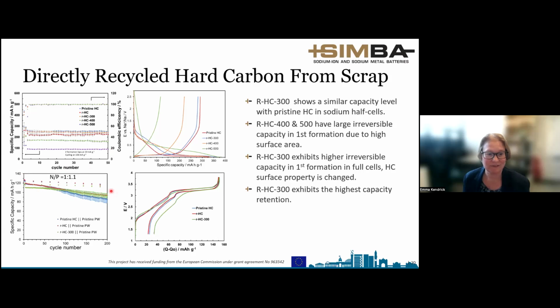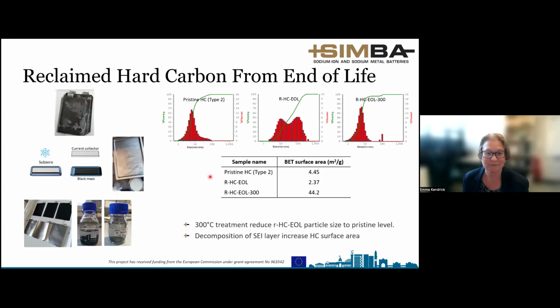Sticking this into a full cell, from the directly recovered, we can actually disperse this back into an ink again and recoat it, and it performs almost exactly the same as the pristine, if not slightly better, whereas the 300 heated, we get a high first cycle loss, so a lower overall capacity in a full cell, but it is cycling quite well.